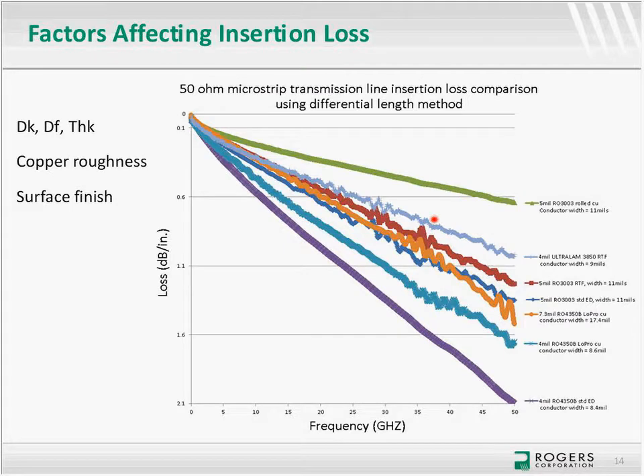So working and talking with your copper and laminate supplier is important in making the proper choice in the balance. Not always do you go with the smoothest copper, because there's always a balance of what happens to peel strength. So depending on the application and the reliability concerns, the question is whether the lower insertion loss with the smooth copper is important enough to overcome the concerns you may have with lower peel strength. So one of the things is the balance of loss and peel strength with the roughness of the copper.